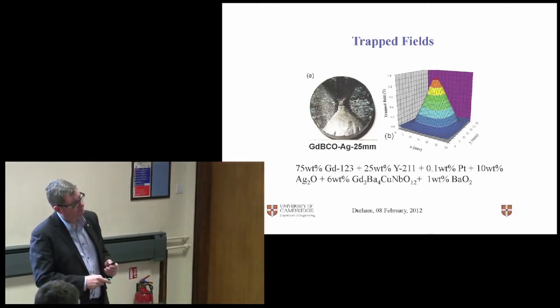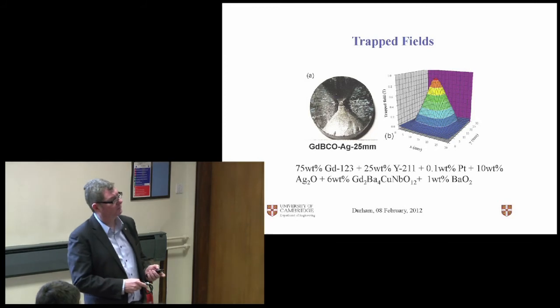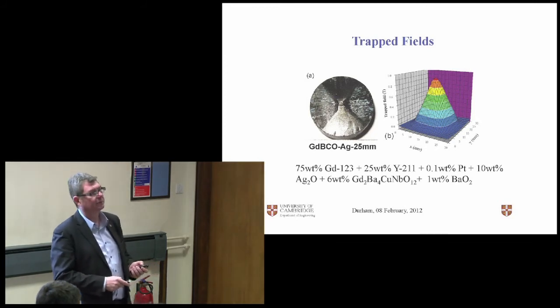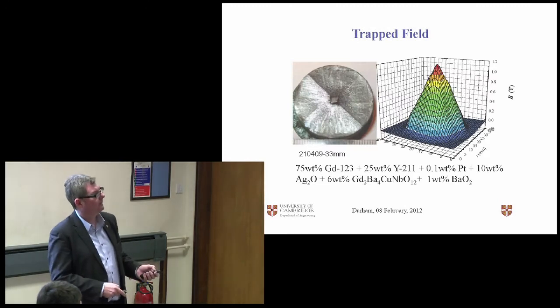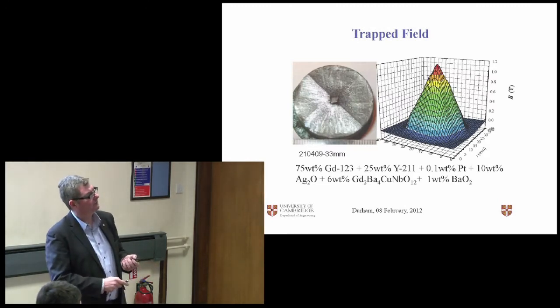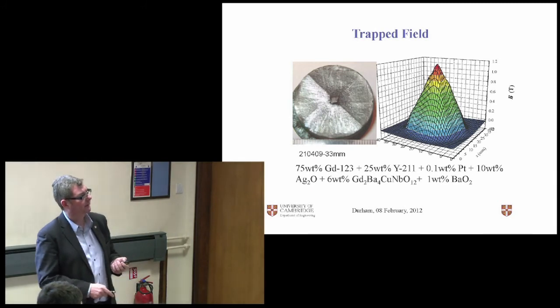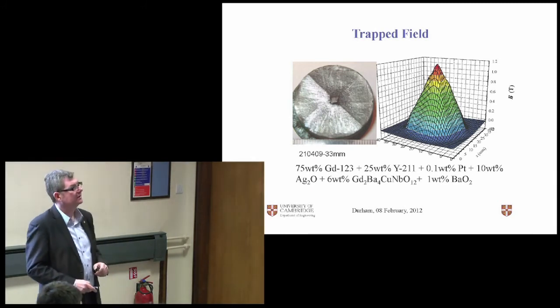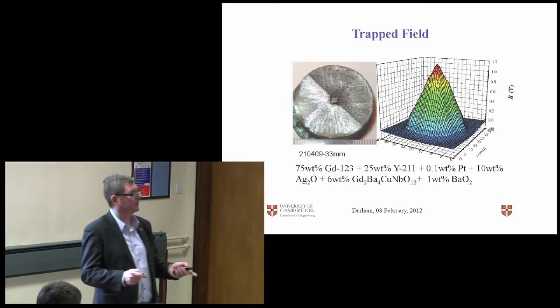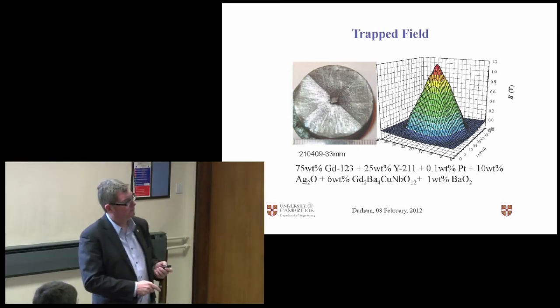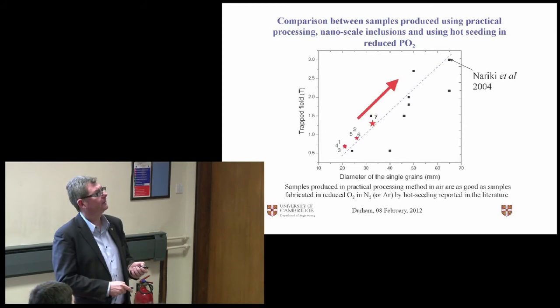But you get this nice inverted field cone, so we've applied a field, we've removed it, and we've scanned a Hall probe across the surface, and you can see this peak field is getting on to 1 Tesla. If you increase the sample size, it goes up to 1.2 Tesla. That's a nice sharp peak there, and there's potential for applications using the geometry of that field cone, and I'll come back to it. But again, this is a slightly bigger sample.